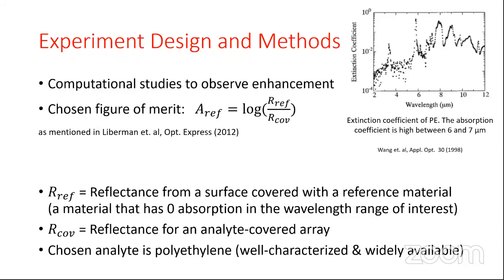And the reference material in this case is basically the same material that has zero absorption in the wavelength range of interest. This is more or less an established figure of merit to show the enhancement numbers so that we could compare. And the chosen analyte in my case is polyethylene, since it's well characterized and widely available. And on the right top, you could see the extinction coefficient of polyethylene.